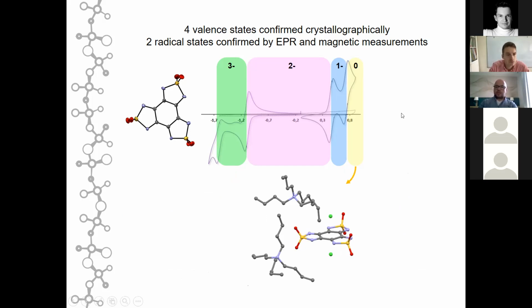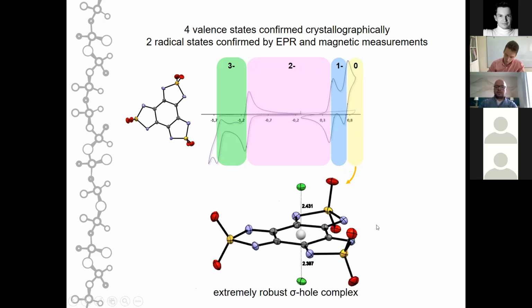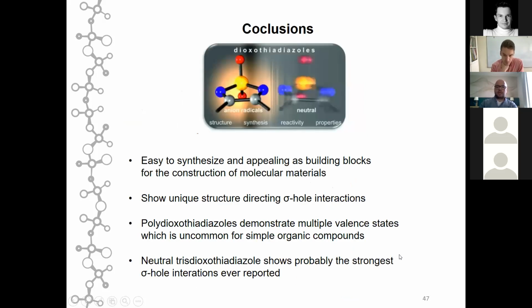We also managed to oxidize our dioxothiadiazole 2-, which is the starting point, to the neutral species. And the oxidation only occurs when chloride ions are present in the solution. This is probably because an extremely robust sigma-hole complex of this molecule in the neutral state forms with 2 chloride ions, with an extremely close distance of 2.4 angstroms between the centroid of the central ring and the chloride ion.